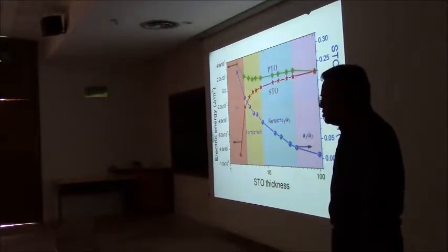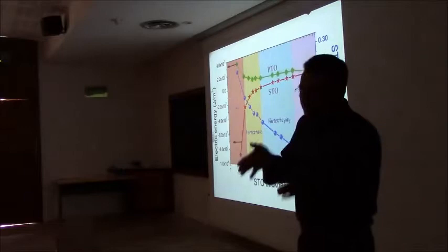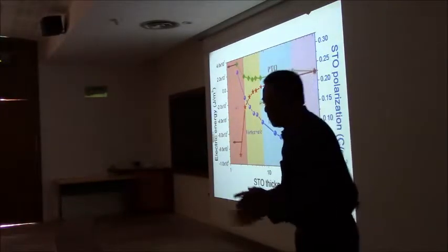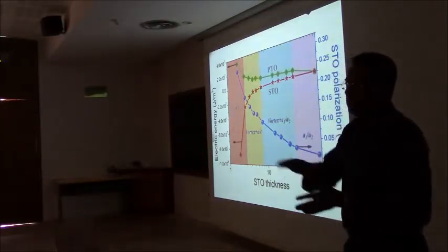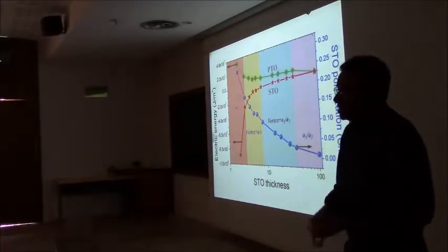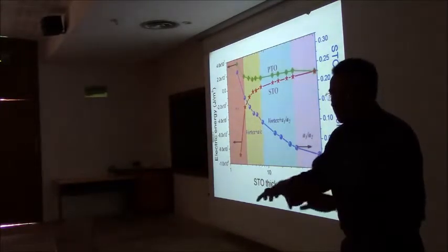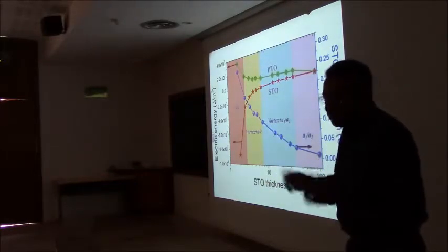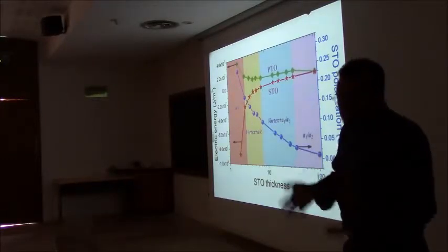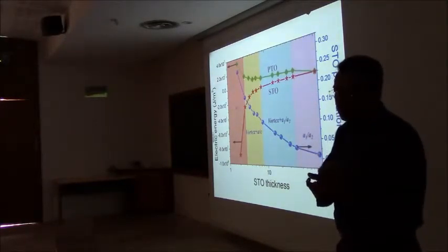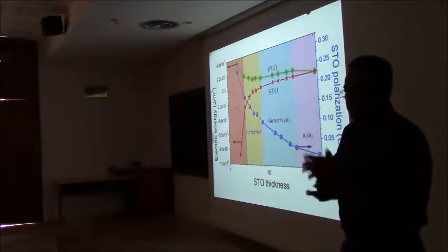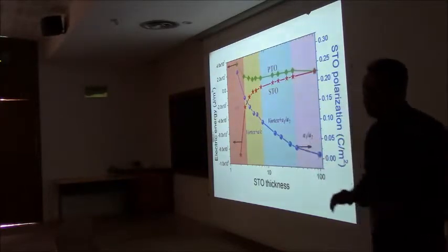Of course, of course. So that particular calculation was for literally the same sample that we grew experimentally. So the substrate, perhaps that's a good point. The substrates that we use for almost all these studies you will see today is dysprosium scandate. Dysprosium scandate is not a square surface, it's a little bit of a tetragonal, rectangular surface. And that's what the calculation was for. And it used the elastic constants for lead titanate, strontium titanate, which are pretty well known. It used the spontaneous polarization for those two materials from published literature, which is relatively well known.